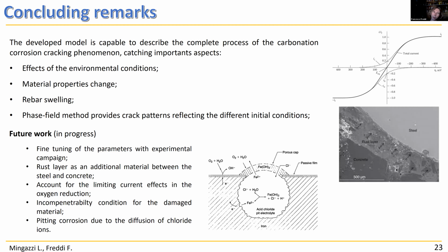In particular, it is crucial to compare the results and to fit the parameters of the model with a very, very intense experimental campaign. The model should be strongly improved, for example, by introducing the rust layer as a third material, because the mechanical property of the rust layer is certainly different from the pristine steel. And I think that other effects should also be taken into account. For example, the concentration of oxygen and the presence of water, humidity, and also the temperature should be taken into account, because these parameters strongly influence the reaction and the corrosion.